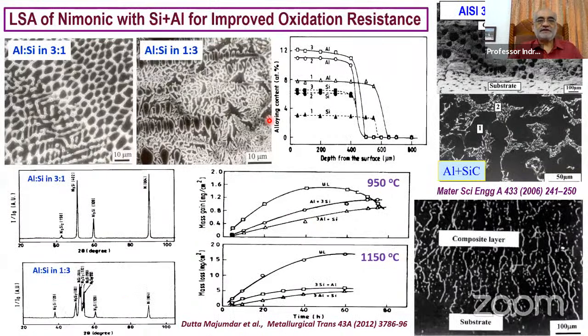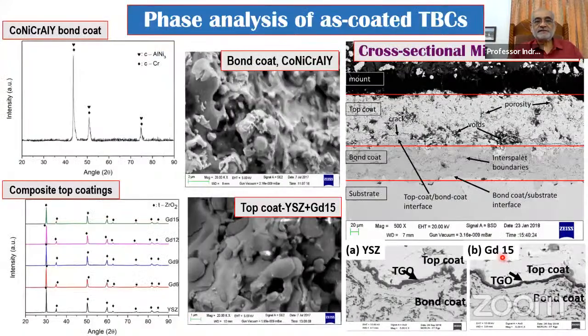And then subsequently, we repeated this with nimonic alloys and also dispersed borides and silicides in stainless steel and developed such composite structures. And borrowing from that, Manoj wanted to create these thermal barrier coatings. So the initial approach was thermal spray followed by laser melting. And we were able to produce this very nice structurally and functionally graded component, with the top layer being oxide, primarily with certain controlled porosity to reduce the thermal conductivity.